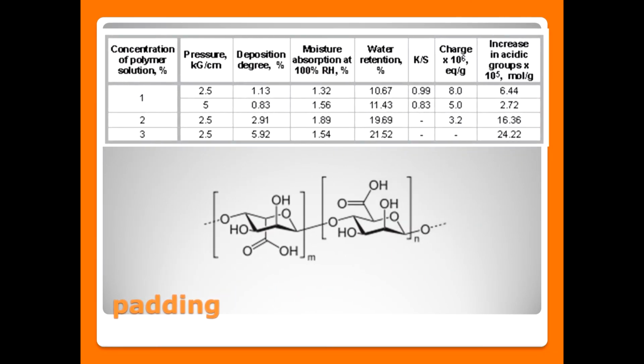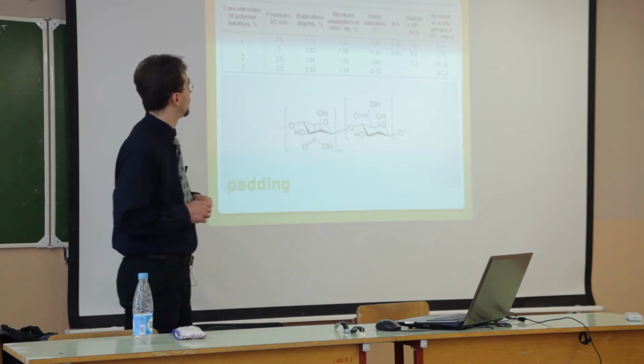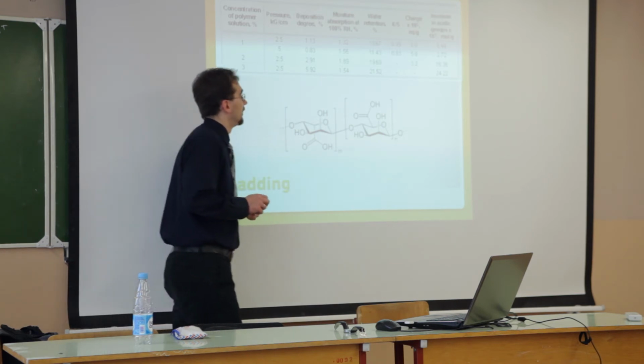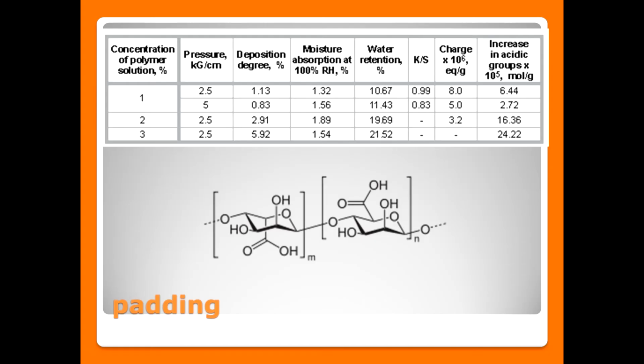As a second layer, we used also alginic acid, and again controlled the deposition degree and the hydrophilic properties. And here I would like to show you K/S. This is the Kubelka-Munk relationship. The main problem with surface modification is always that you need some advanced techniques to control the surface after modification.